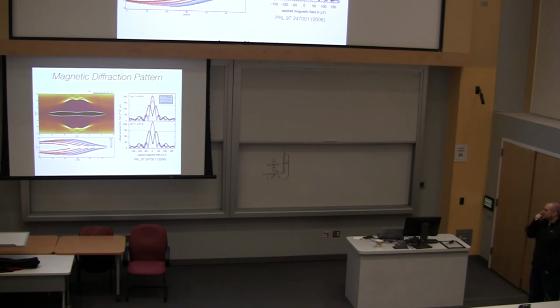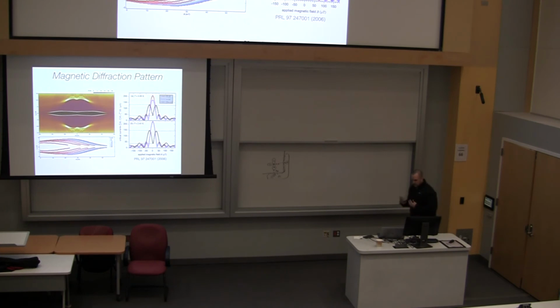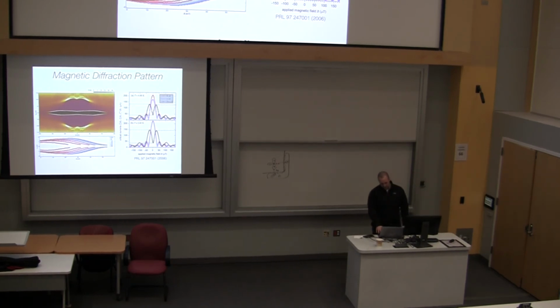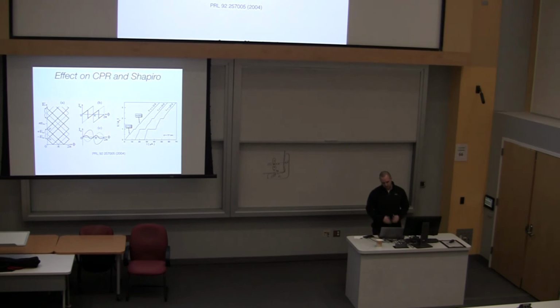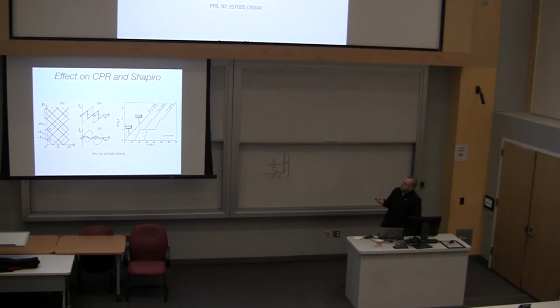The other place, and the place that I've shown here, is in junctions where the weak link is made of a ferromagnetic material. And in these junctions, the exchange field provided by the ferromagnetic material has an effect on the Andreev bound states such that some of the Cooper pairs transfer straight through the junction with a phase difference of 0, the others with a phase difference of pi. And this destructive interference gives you a minimum around B equals 0. So we have this in a material that is not expected to have anything interesting with, so this is just the resulting measurements.